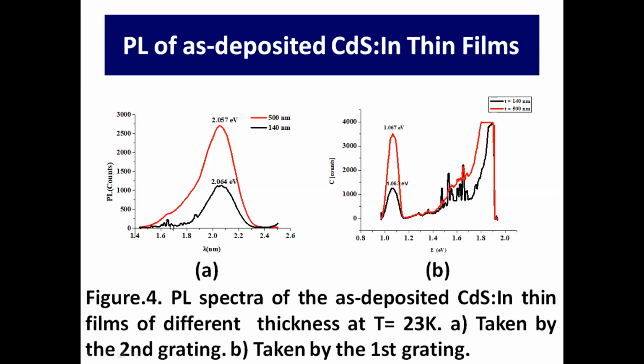And you see there is a structure and sharp peaks in the PL spectrum of the thinner film, and this is due to the presence of nanoparticles, because as I mentioned before, the average grain size in the thinner film is about 100 nanometer, which means there will be an effect of this nanostructure on the PL spectra.